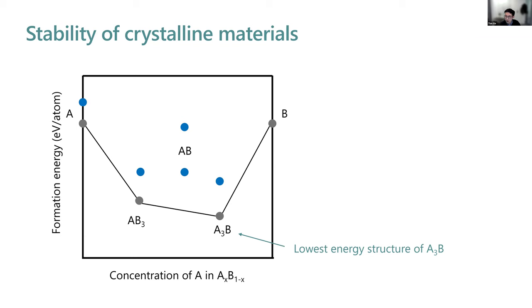But if you know this energy, then we can understand which ones are stable using the so-called compositional phase diagram. Here, I'm plotting all the materials for A and B in this XY plot, where the x-axis is the ratio of A in A and B, and the y-axis is their formation energy. Materials are stable if they are on the lowest convex hull of this plot, basically the gray dots here.